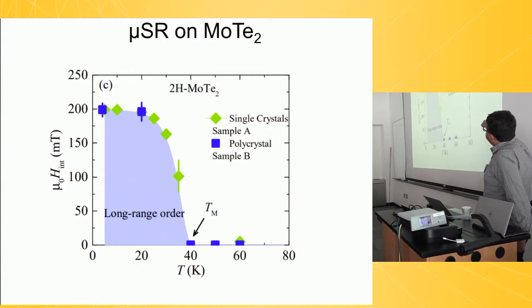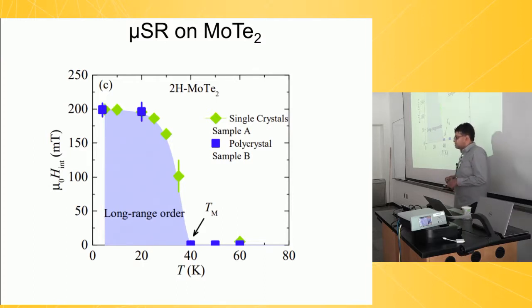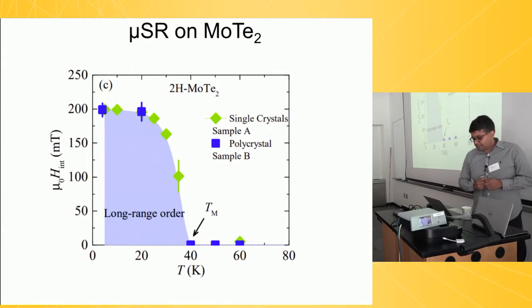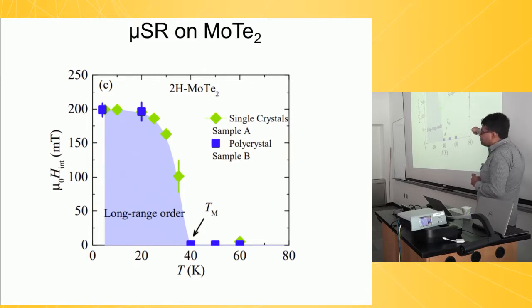We measured this as a function of temperature, and you see it goes down, and around 40 Kelvin, we stop seeing these coherent oscillations in the muons. We can extract back from the frequency of these oscillations what the internal field is that the muons are seeing. That's the field, 200 millitesla. 200 millitesla is not a small number. That's a good magnet.